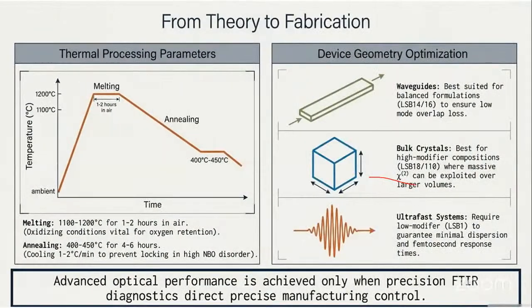Now I had already briefed you how the process has to be. It cannot be a direct quenching technique. It has to be a step process. Even post melting temperature, it has to be annealed at a certain temperature. Annealing has to happen at 400 to 450 degrees Celsius, and it has to be held for 2 hours or 3 hours.